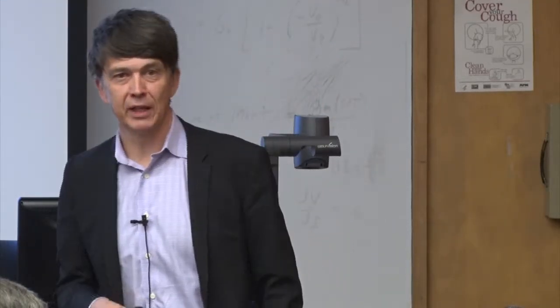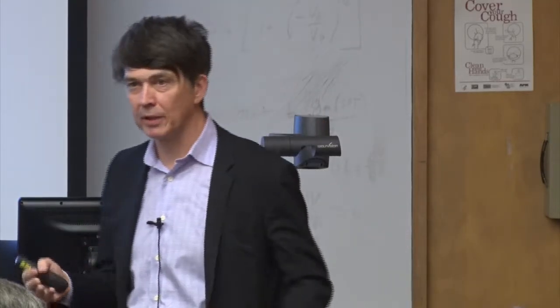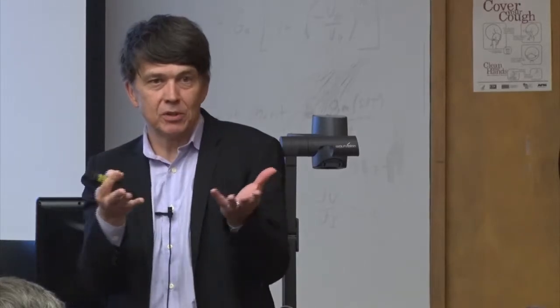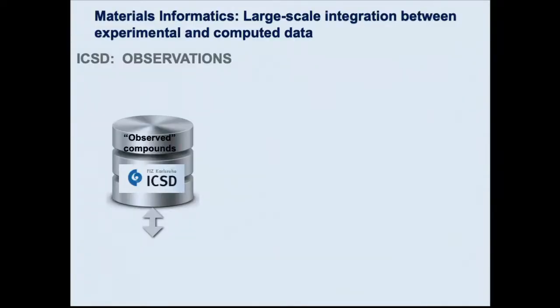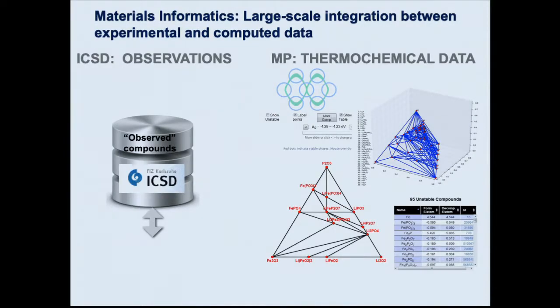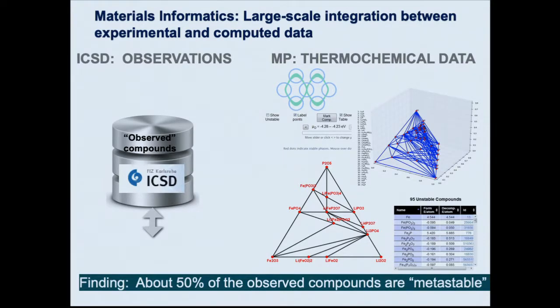Today you can investigate that, because we know how many compounds are observed, right? We have a list of observations, which is the Inorganic Crystal Structure Database. And then we can, in high throughput, calculate phase diagrams and enthalpies of formation and mixing. And so we can compare the two. So the question is, how much of the world is metastable? It turns out about 50% of known compounds are metastable. Order of magnitude. It's a bit of a tough criterion to slice exactly, but it's order 50%.